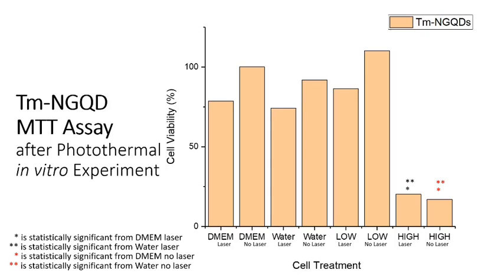So what we're seeing with the thulium NGQDs is that there's no statistical significance between either of the low concentrations and the water or the DMEM. So that tells us that it's not really dying in the low concentration from toxicity, and that it's not dying from any photothermal properties. Otherwise, we would be seeing a difference here.